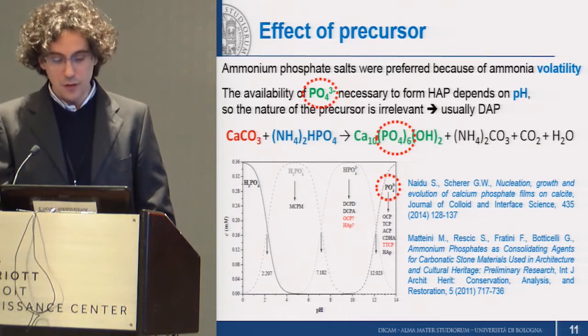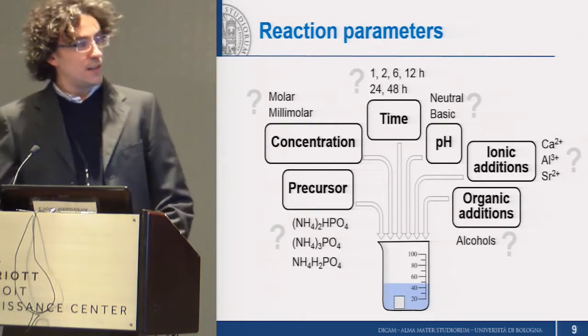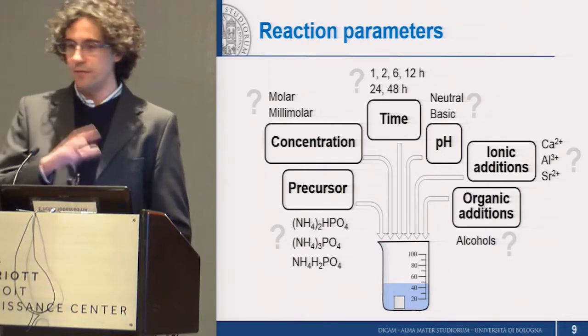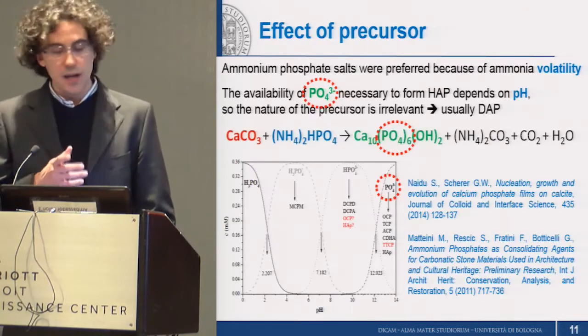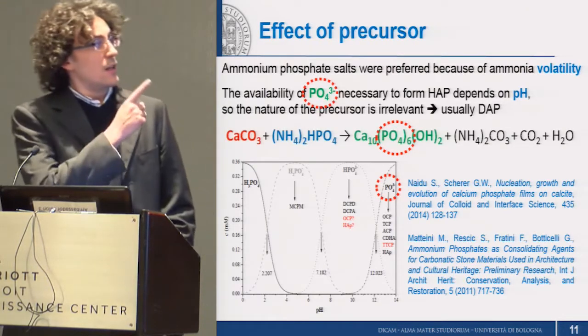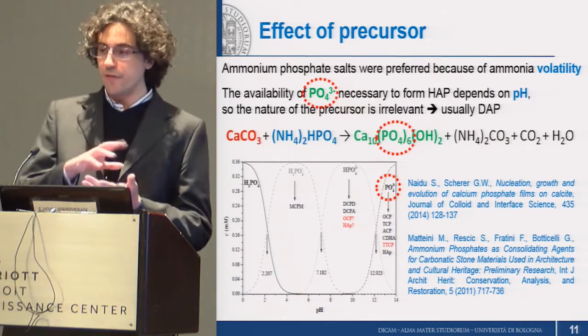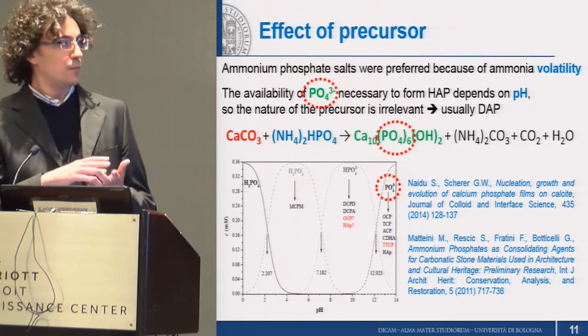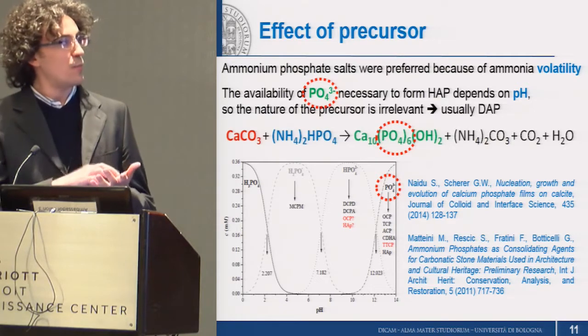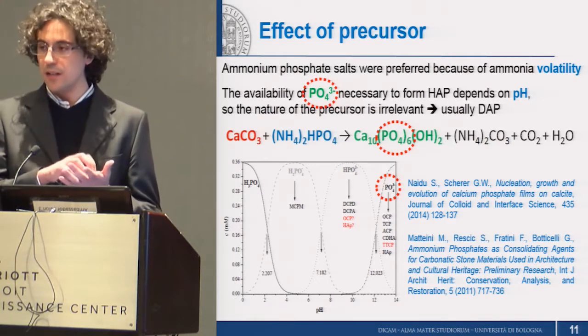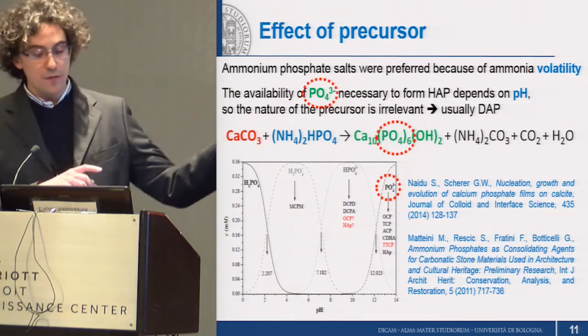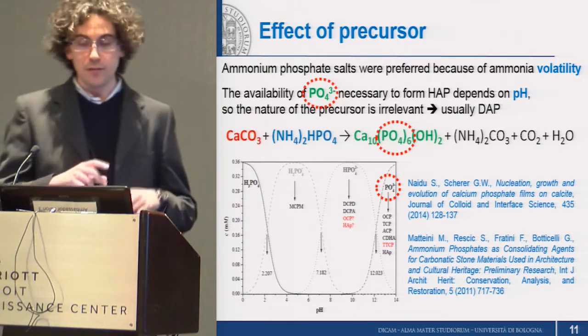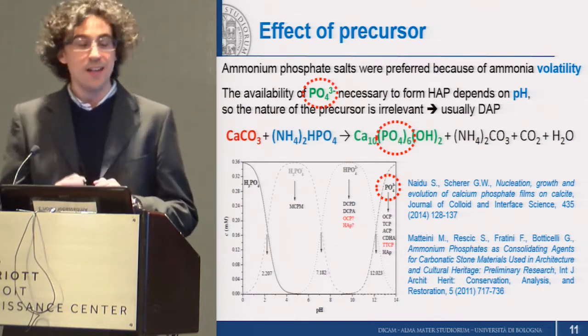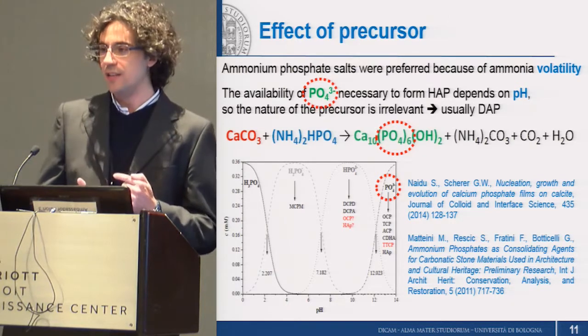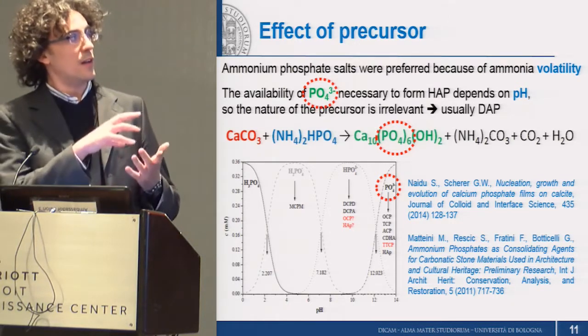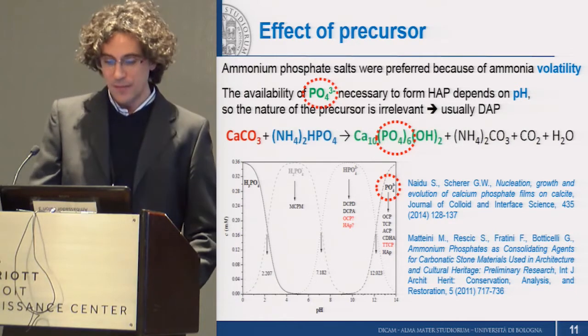Then among the different phosphate salts that could be used, you can see some examples here. So in the end, we found out that it's basically irrelevant what phosphate salt is used as long as pH is controlled, because it's pH that controls the amount of phosphate ions, intended as PO4 3-, that are available, because these ions are the ones that are needed to form hydroxyapatite, while, for instance, HPO4 are useless in our case, not to say counterproductive, because other phases, such as brushite or calcium hydrogen phosphate, may form.